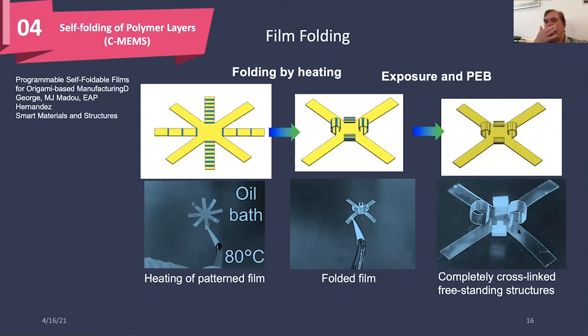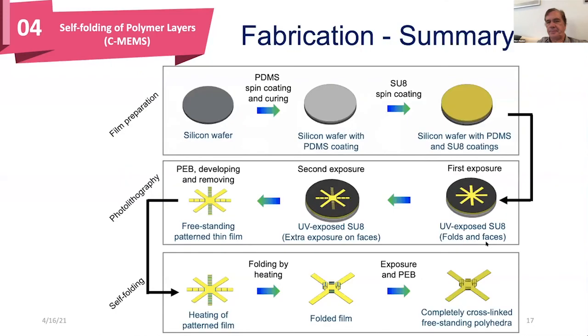And then again, we can go from these polymer shapes to carbon shapes. So that's fabrication in summary. Silicon wafer, PDMS spin coating and curing. This is the silicon wafer with that PDMS. Now SU8 on top of the PDMS. First exposure to cross-link these areas somewhat. Cross-linking in a second exposure a bit further, so you distinguish faces and folds, and then taking these shapes off.